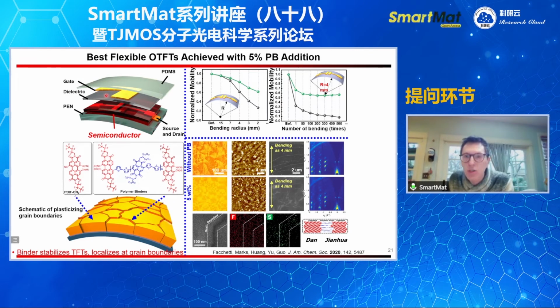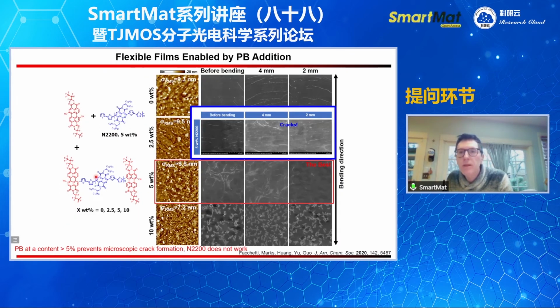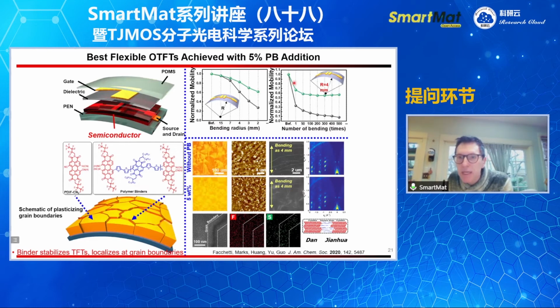We made transistors, and this is comparing. Here we bend the devices at 4 millimeter, and the black is for the film without the additive. You see the mobility decreases, and then it continues to decrease. It never stops. Instead, if you add about 5% of the polymer here, the mobility decreases at the beginning, but then it stabilizes. Basically, it tells us that at the beginning you form some cracks.